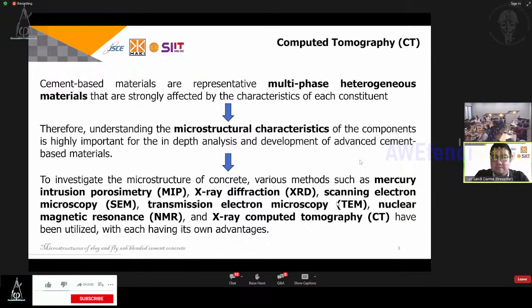Okay, as you can see here, cement-based material is a representative multi-phase heterogeneous material that is strongly affected by the characteristics of each constituent. Therefore, we need to understand the microstructural characteristics. Up to now, we apply MIP, mercury intrusion porosimetry, and X-ray diffraction, as mentioned by Januarti Senpai. Next, SEM, scanning electron microscopy, which can be combined with BSE, backscattered electron, and then transmission electron microscopy, or TEM, nuclear magnetic resonance, or NMR, and finally X-ray computed tomography.